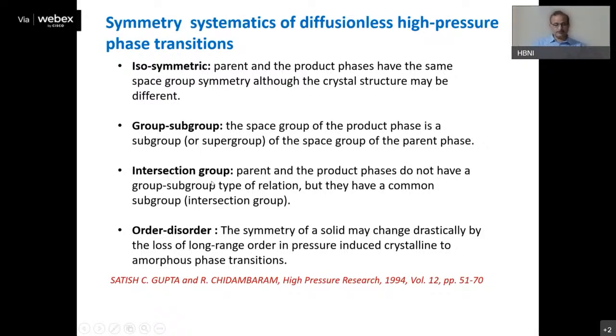And then there can be an intersection group relationship, which means there can be some intermediate phase which is symmetrically related to the parent and the daughter phase. And then there is one case which is called the order-disorder phase transition, in which the symmetry is lost. There is a drastic change in the long range order. An example is pressure-induced amorphization. This list covers many of the phase transitions at high pressure, but other than these, there can be reconstructive phase transitions also, which do not have any symmetry relationship. For example, the graphite-diamond transition. Those kinds of transitions can be better studied by examining the atomistic evolution of the system through theoretical calculations.